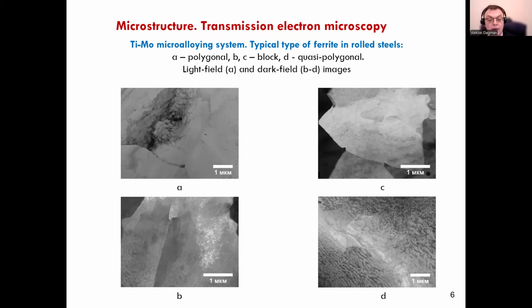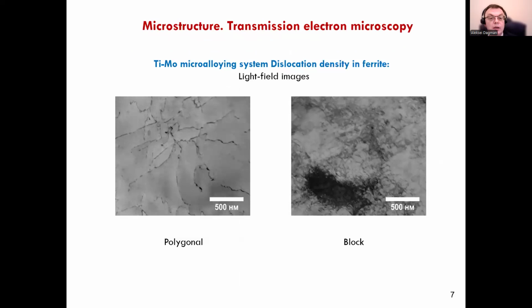The shape of the blocks in the CF varies from approximately equiaxed, figure B, to moderately elongated, figure C. In samples with a higher carbon content, quasi-polygonal ferrite is present in the microstructure, figure D, with approximately equiaxed blocks, the size of which is close to the size of PF grains. It was found that the density of dislocations in polygonal ferrite and quasi-polygonal ferrite is low, and their distribution is chaotic, figure A. The density of dislocations in the block ferrite is high, figure B.